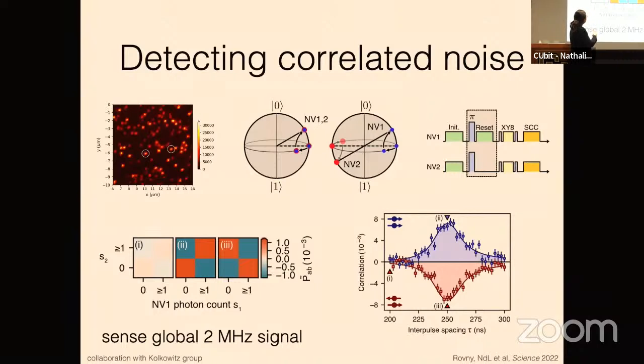So this is a scanning confocal microscope image. Each of these bright blobs is a single NV center. We can pick out 2 NV centers and then do this measurement. So this down here is data where we are binning conditioned on measuring 0 photons in NV1. Do we see 0 photons in NV2, or do we see a bright NV1 or bright NV2? And you can see that there are essentially no correlations when you don't expect there to be. And then if we apply this correlated noise, you get this nice checkerboard pattern, which shows that when NV1 is bright, NV2 is bright.